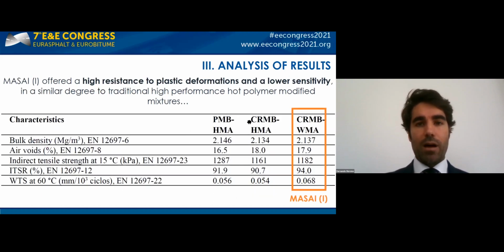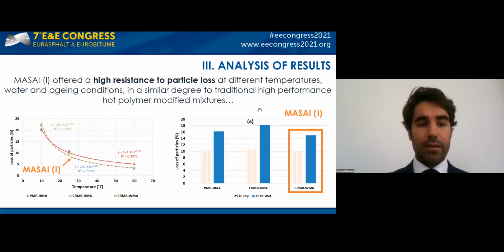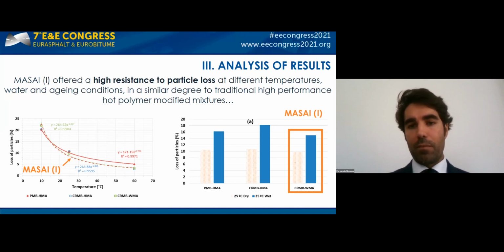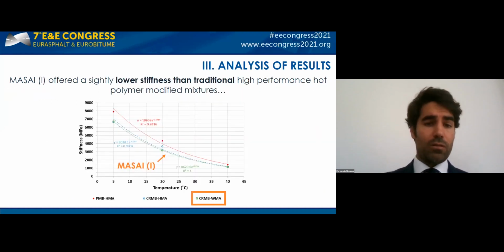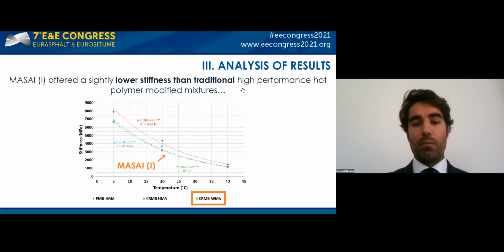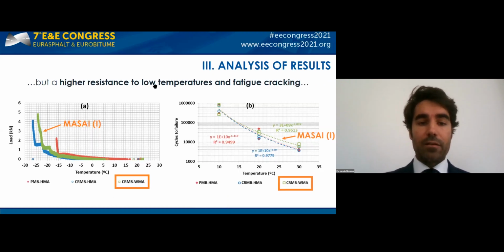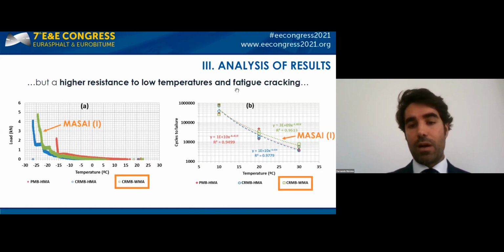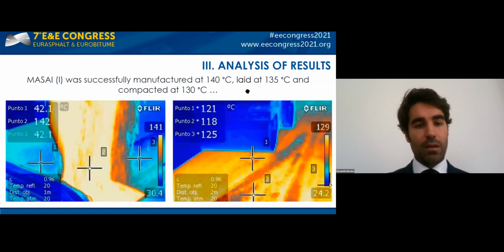The MASAI grade 1 design offered a high resistance to plastic deformation and a lower water sensitivity, as well as a high resistance to particle loss to a similar degree as traditional high-performance hot polymer modified mixtures. On the contrary, it offers a slightly lower stiffness than traditional high-performance hot polymer modified mixtures, but a higher resistance to low temperature and fatigue cracking.